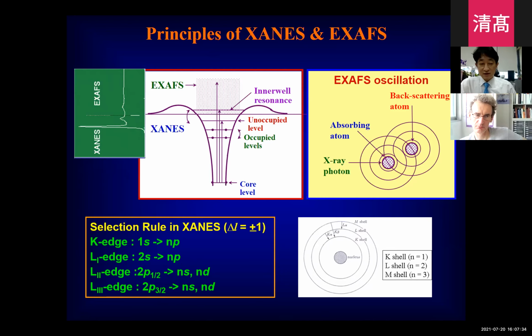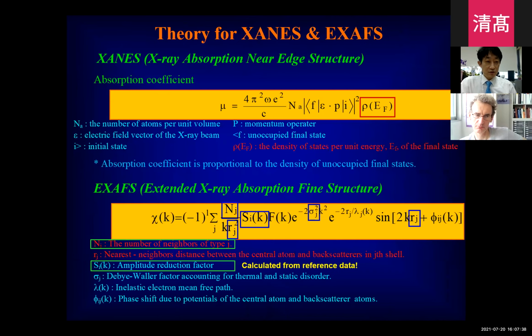This is the selection rule for XANES. In XANES, we have the formula for the absorption coefficient. I want to emphasize that the absorption coefficient is proportional to the density of the final state. So from the intensity, we can get quantitative information about the density of the unoccupied electronic states.